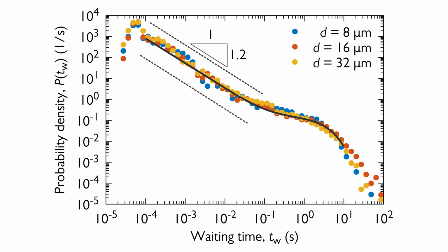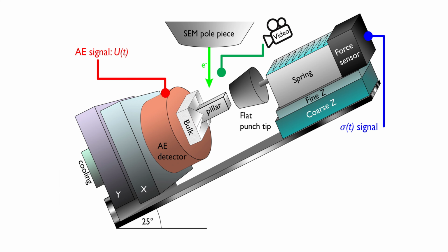The distribution of waiting times between subsequent acoustic emission events, a key measure of temporal correlations and clustering in temporal processes, was also analysed. The power law decay for small waiting times below 0.1 seconds corresponds to the correlated temporal clusters originating from the same plastic event, often observed as a single stress drop. For larger times, a plateau with an exponential cutoff is observed corresponding to a Poisson-like process of uncorrelated signals coming from different plastic events. In summary, the most important results are as follows.